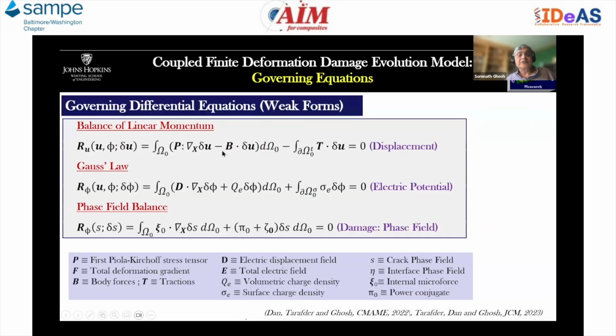These are the governing equations. There are three types of governing equations. One is the balance of linear momentum, or the equilibrium equation corresponding to the displacement field. These are all for finite deformation. As you can see, finite deformation, damage field, and it is also coupling the electrical field. The electrical potential field is represented by the Gauss law, and the phase field balance equations correspond to the damage field in the microstructure, also representing the interfacial debonding.